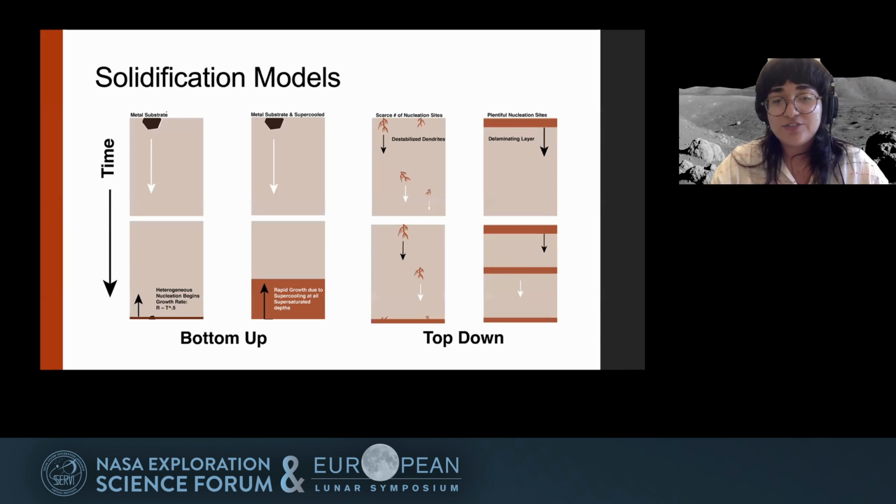And what we're doing here is describing what could possibly happen for a lunar core with a given composition and a given supercooling. On the very left, we have no supercooling, but it's just reached the liquidus at the very bottom and a substrate has been delivered. So this is as close to canonical growth as possible. Next, we have a core with low sulfur and it's partially supercooled, but not all the way to the CMB. So a substrate still needs to sink. And once it does, all supersaturated dust will solidify extremely quickly, basically instantaneously on lunar timescales.